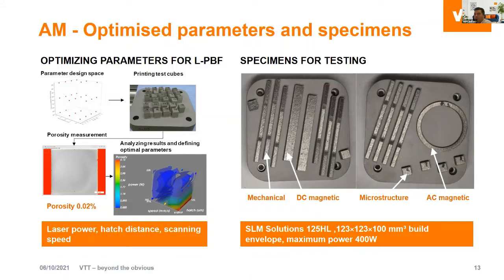So we have to utilize some kind of multi-parameter optimization, looking at all of those parameters simultaneously and then selecting the best possible candidate parameters for the printing job. And depending once again on what we would like to measure, we need different types of samples. We also need quite a big amount of samples because of the post treatments and heat treatment development. So typically it has been done so that first we optimize the microstructure based on metallography and study how the heat treatments are affecting those microstructural features, and then move to measure mechanical and magnetic properties of these materials.